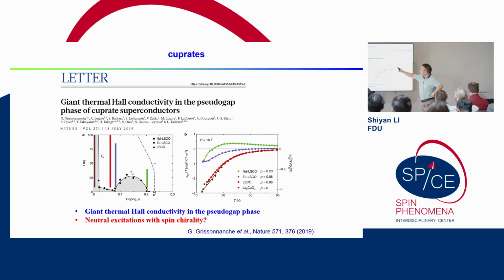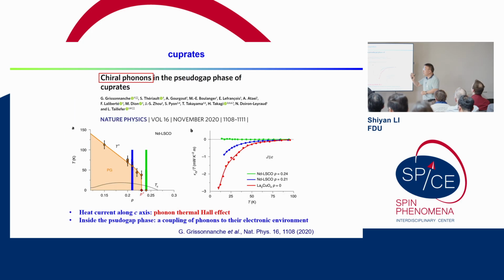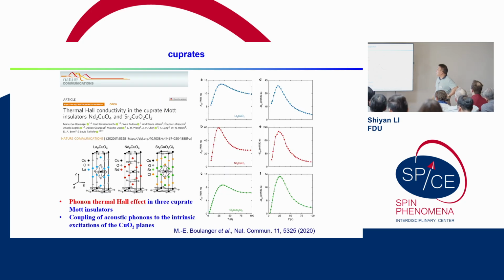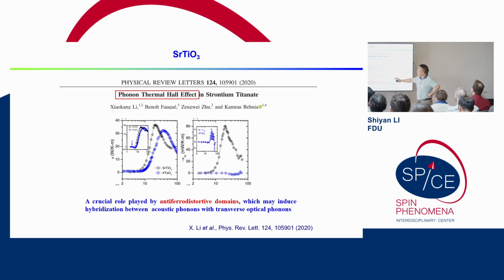The first paper was immediately related to the pseudogap phase. But for this cuprate compound, the single crystal is very large, so you can easily cut it and put the current along the c-axis. They found a similar signal, so we immediately realized it cannot be an electronic contribution in the plane. So in the title it's the chiral phonon, because along the c-axis. There are more measurements on the parent compound of cuprate. And this is the first measurement of a non-magnetic compound. This is STO.